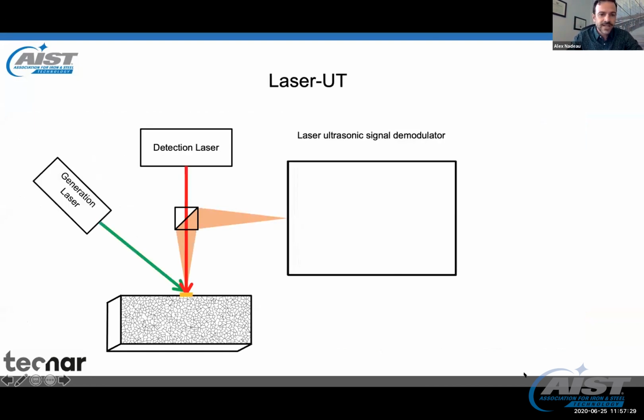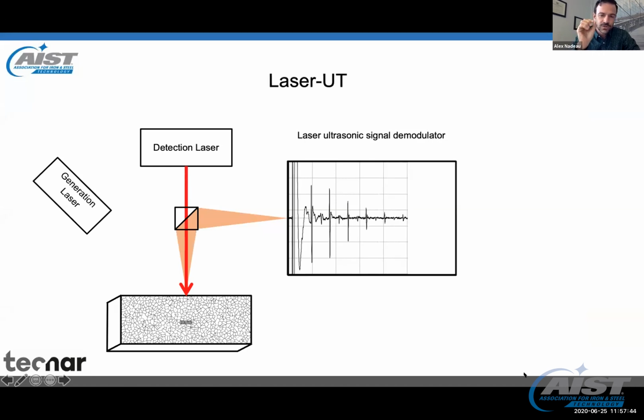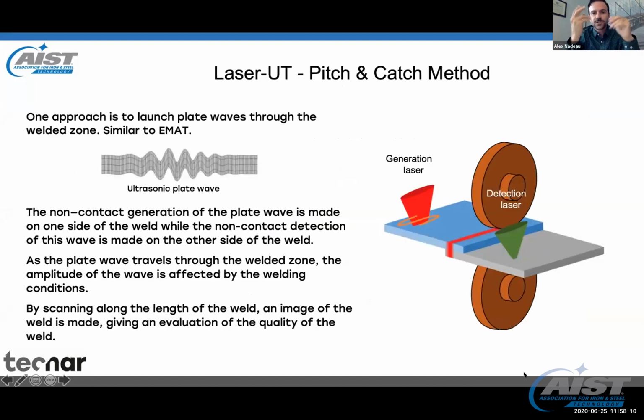So here's a small schematic of how it works. We shoot the laser spot, and basically the detection laser shines for a longer period of time, enough to capture the ultrasound. This is a real laser ultrasound A scan, as we call them, and you can see that the resolution of the echo is quite high frequency. So it allows for a lot of analysis, namely it allows for attenuation measurements that can reveal the microstructure of the material, which is like the second wave of using laser UTs, not only for defect measurements, but for microstructure. So I'm going to talk about two ways of using laser UT.